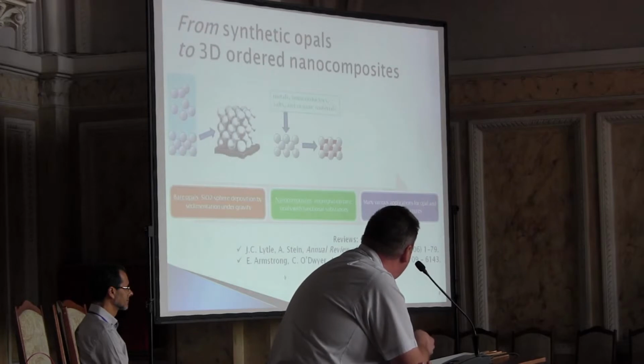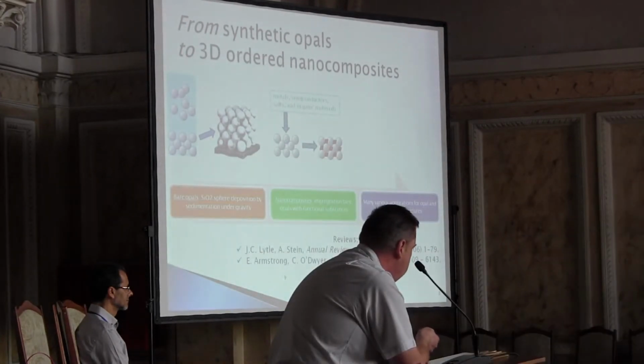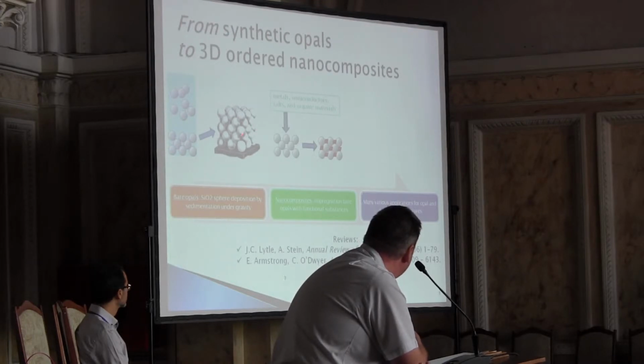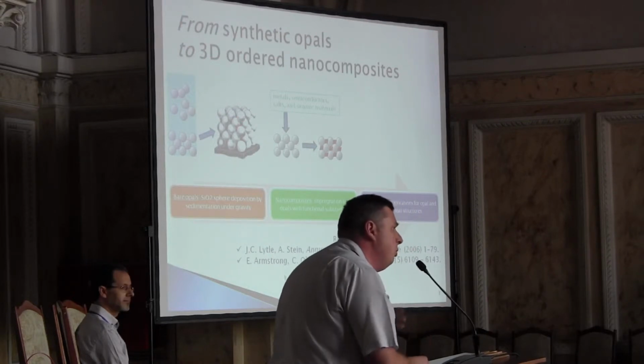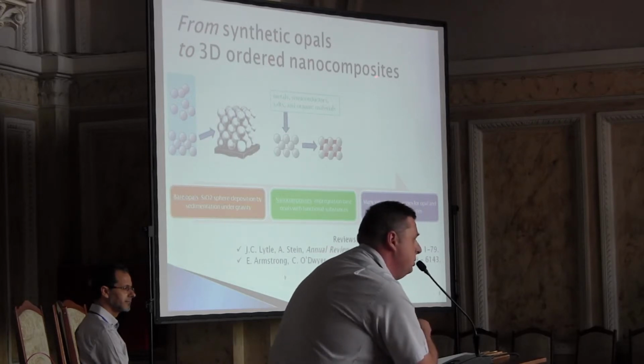And when you crystallize some substance in opal pores, the crystallization in pores may stop the penetration of the solvent inside opal pores in further cycles.